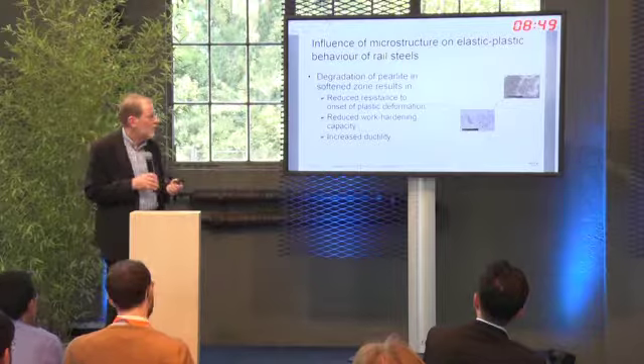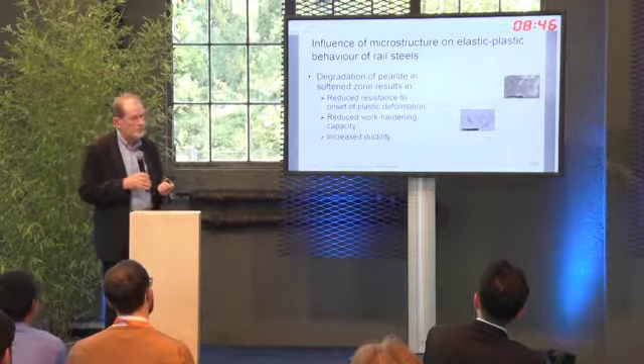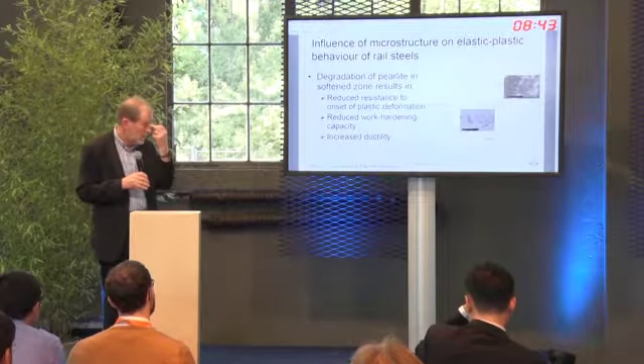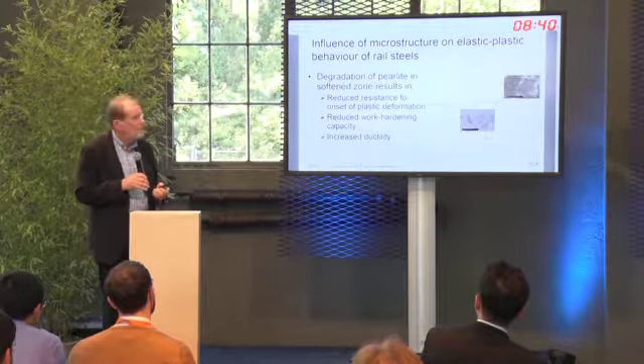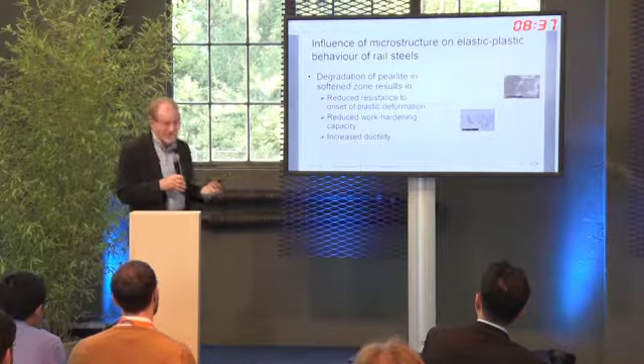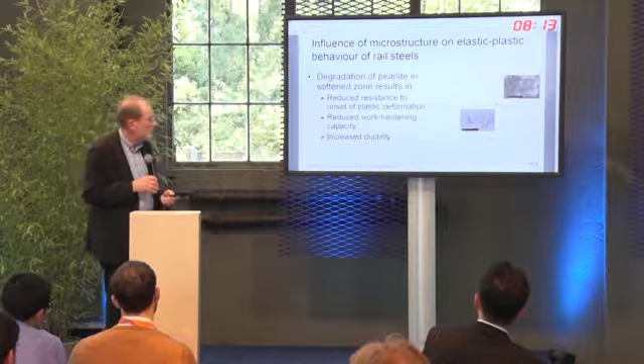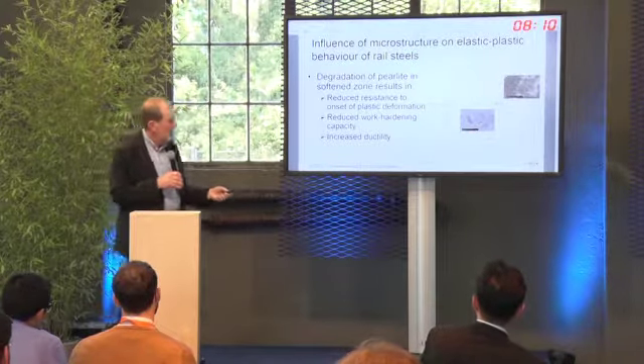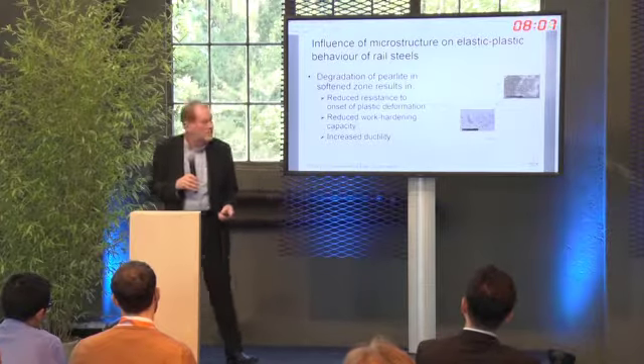Just to illustrate the effect of that hardness or microstructure variation on the deformation behaviour, this is just some tensile results for two representative microstructures. This is actually in a domestically produced, Australian domestically produced heat-treated rail that actually has a softened zone in the middle of the head. So on the top is the microstructure for close to the gauge corner of the rail, pearlitic microstructure, and you can see the stress strain behaviours as you'd expect for a pearlitic rail steel. But if you go into the softened zone, it's quite a noticeable change. You actually get a yield point elongation.